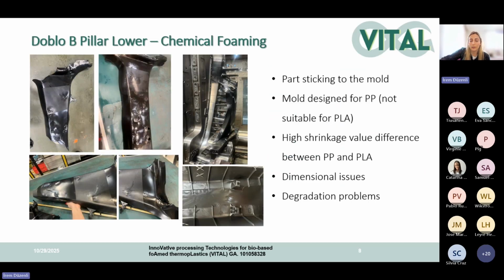And also, I want to give brief information. I already mentioned that we have some degradation problems with PLA, because PLA degrades at higher temperatures, and also our injection molding machine has big capacity. So when PLA waits in the screw, it degrades. You cannot wait after the trials. You need to continuously continue the injection.